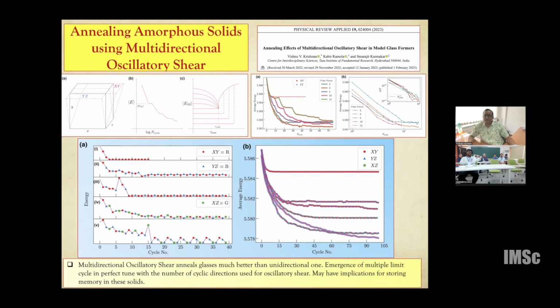0.7. So what is interesting is this nice plateau appearing. If you basically shear it along one direction, then it saturates there. Then again, if you do it in another direction, then you again have a cascade of events, leading to a new minima. And this structure continues. So there is some sort of compactification, plotted in this figure, where you can see the average energy as a function of the number of changes in this direction. That's like a compactification process.